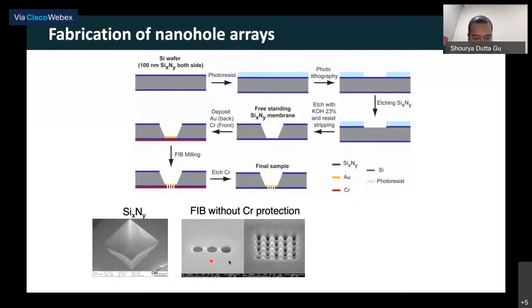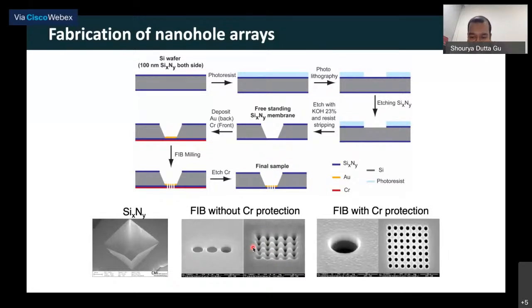So if you notice here, the walls are not very flat. And if you make very small structures, these are 50 nanometer holes, you see that you get hills rather than flat walls. However, if you put a layer of chromium, you get walls which are very, very flat and sharp. And these are the typical holes that we have fabricated for this particular structure.